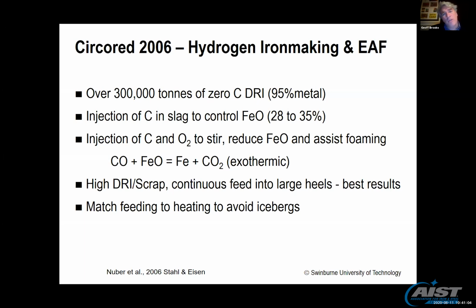And they also found that when they used a large amount of DRI compared to scrap, it was best to feed continuously into a large heel, which makes sense, right? You have a big pool of molten metal, and you try to feed continuously or semi-continuously into that large heel. When you do that, they mentioned it's very important to match the feeding to the heating so you don't get large icebergs. So you're going to have to pay some attention to matching the heat input to the heat requirements, because you have the potential for a whole lot of unmolten iron sticking together and forming an iceberg, which is not desirable in an EAF, of course.